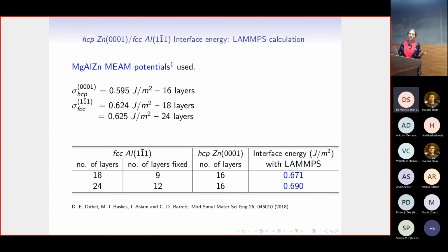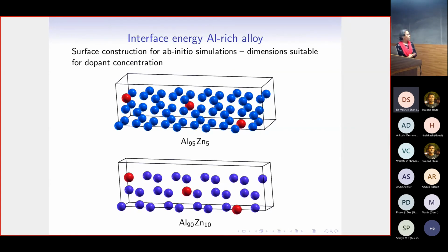Okay, but what about when we have an alloy? We want to see a surface of a pure metal. Calculation for the surface of a pure metal is simple because I have a very small simulation cell that I can work with. But when it comes to an alloy, I need to have the correct dopant concentration for the alloy, and when I build the surface, that surface should be able to reflect that correct dopant concentration that we have. Okay. So for the aluminum rich alloys, now we have to do the surface generation a little differently.